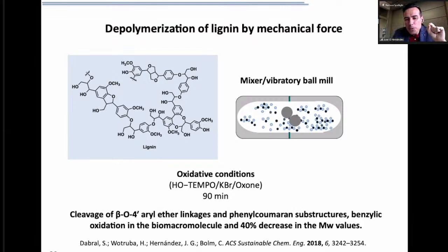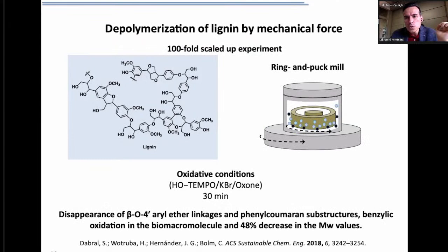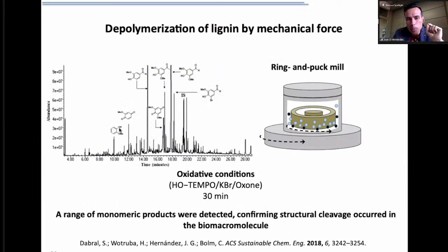We were working at the milligram scale at that moment, and we wondered whether it would be possible to carry out the reaction at a higher scale, to demonstrate that indeed scale up is achievable by mechanochemistry. So we decided to do the reaction on the gram scale, I think, if I recall correctly, 10 gram scale. And to do that, we used a ring and puck mill. What we observed was that the reaction proceeded even better. With only 30 minutes, we managed to achieve a higher decrease in molecular weight within the lignin biomacromolecule. And immediately we observed the presence of those aromatics that we were looking for. So somehow this change in technique was favoring the reaction to proceed much better and in shorter time.